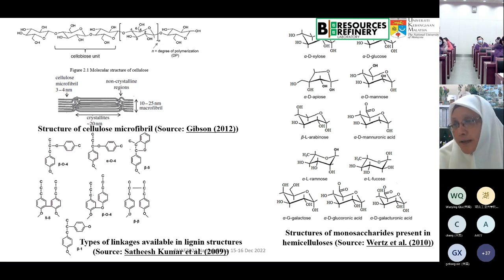And the structure of lignin is very complex, which is why I keep asking how to make it stable, because lignin has lots of conjugated double bonds, which are very active as far as UV is concerned, and will tend to polymerize. Unlike hemicellulose, which is sugars and can easily be attacked by fungi and so on, that makes this material very biodegradable. The same goes for cellulose, which is made from glucose units in a very long chain, but because cellulose has amorphous and crystalline areas, it is more resistant compared to hemicellulose, which can easily be extracted from the materials.